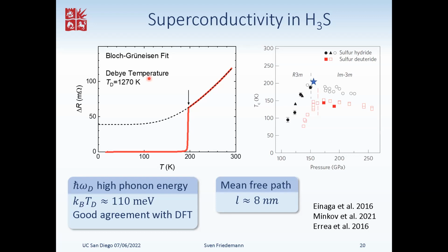Most importantly, we can take these resistance measurements and convert them into resistivity using the approximate sample dimensions that we can observe, so about 15 micron laterally and say 2 micrometer thick. The resistivity, in the extrapolation to zero temperature, is of the order of 7 micro-ohm centimeters, so a goodish metal. And we can convert this using the existing Hall effect measurements into a mean free path, which comes out at about 8 nanometers.